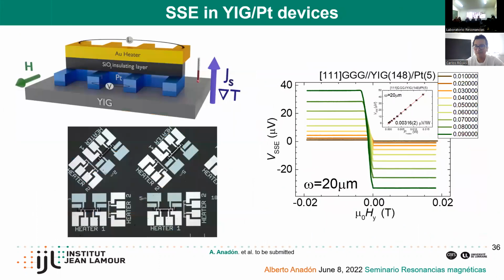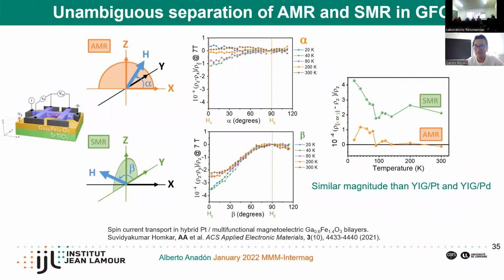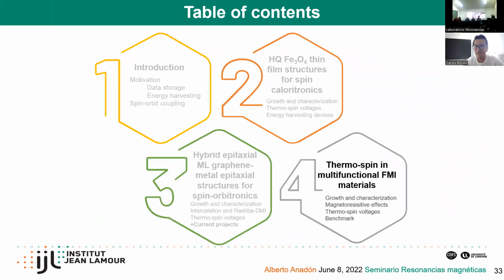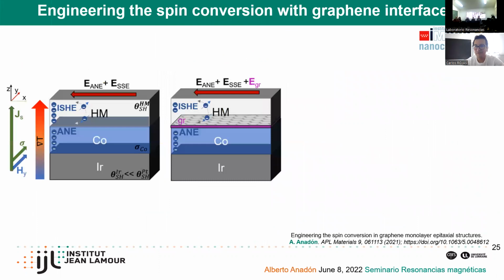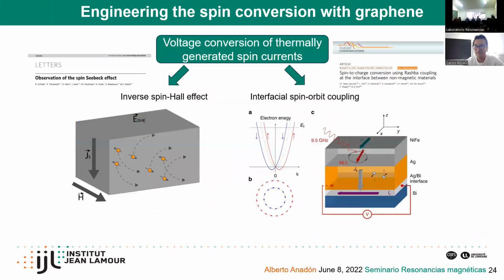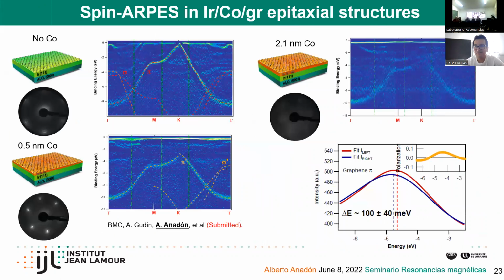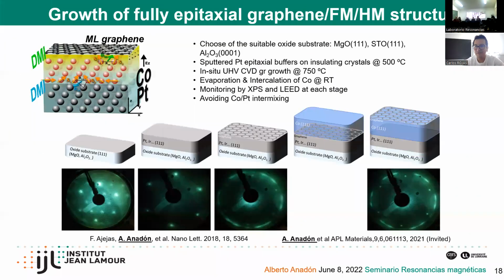So let me go back to the slide where I discuss this. Here. What's normally done is chemical vapor deposition. Normally what people do is you have a copper monocrystal, for example, or iridium or platinum monocrystal. You heat this crystal to very high temperature, normally about 1000 or 800 Kelvin, and you put a bit of gas in your chamber. This gas, when it reaches the surface of your metal, it breaks the bonds, usually ethylene, but you can use a different one.